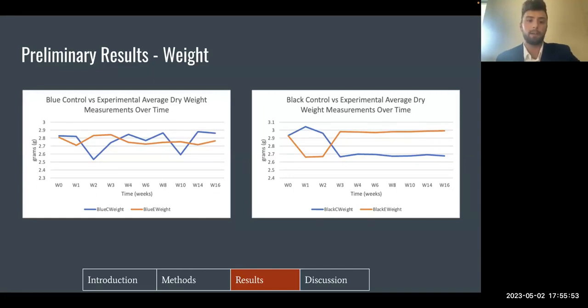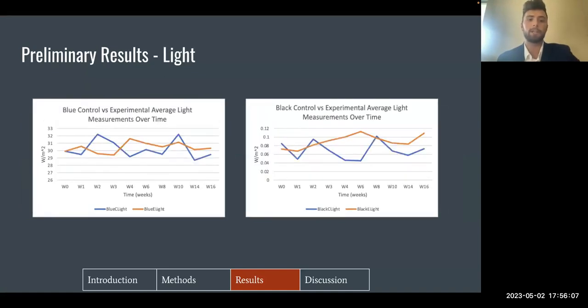It's possible that although the seawater was sterile and the masks were rinsed, there could be some degree of biofilm, salt residue, or rusting that could contribute to weight and light inconsistencies, as you can see here. There could also be variations in the masks' initial weights, but my plan is to analyze each individual mask more in depth to see if there are any noticeable trends in degradation. Obviously, my hope is that there are, and I'm hoping that the microfiber counts and CI measurements provide a more precise look at what is actually happening to the masks.